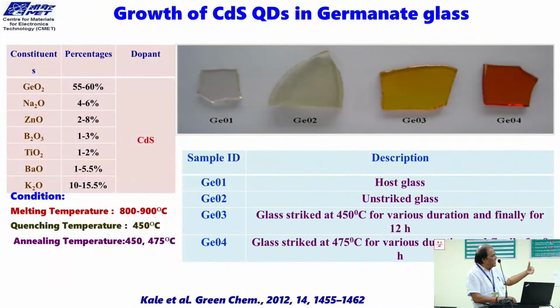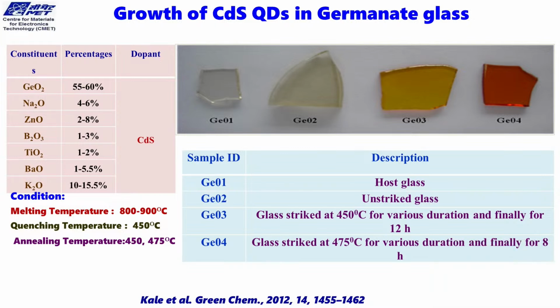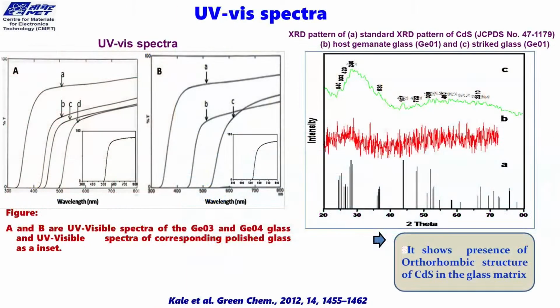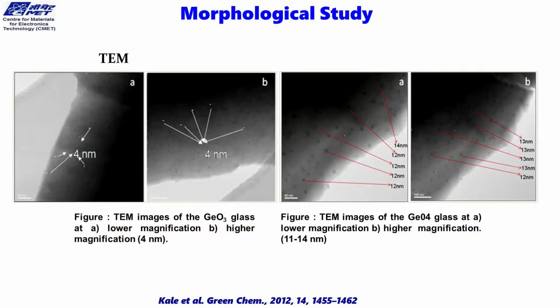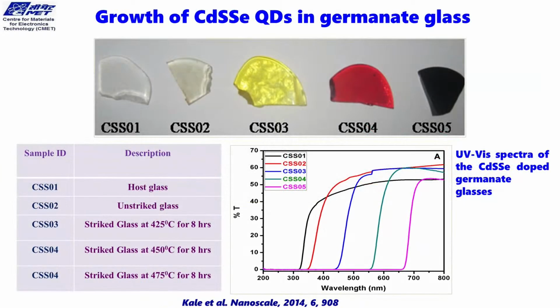Then we developed another glass kind of structure. In a different system, we generated particles inside the glass, and we found that such structures can give much more hydrogen evolution. You can see here these nanoparticles inside the glass, so many very tiny nanoparticles. Under the microscope, you can see 12 to 14 nanometer scale particles inside the glass. You can see the 300 nanometer to almost 700 nanometers.